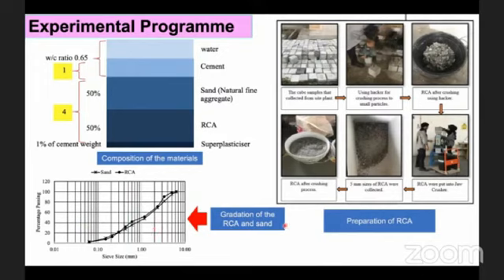And this is the gradation of the recycled concrete aggregate and sand. And this is the preparation of recycled concrete aggregate. In this study, the waste material was tested cubes that we collected from a batching plant, which have the same grade of concrete, 25 to 30 megapascal.